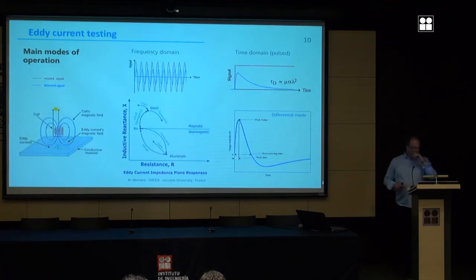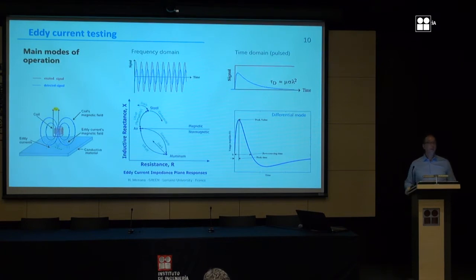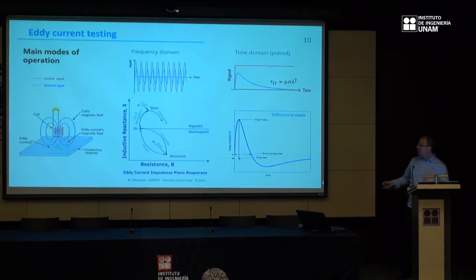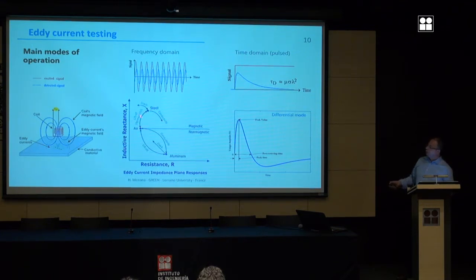Go forward. We have two main modes of operation. We can operate in the frequency domain, where we sense the impedance variation of the coil, and we use an impedance plane response of the coil. We start from the self-impedance of the coil in the air, and then when we put the coil above a material, if the material is ferromagnetic, the impedance will vary this way. We go this way. This is the effect of the lift-off. What's shown here is the typical response of an eddy current sensor above a material. If it's ferromagnetic, it will go here.